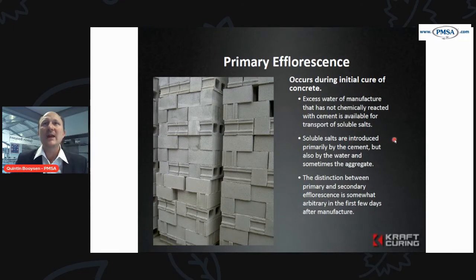The soluble salts are introduced primarily by the cement, but also can be introduced by the water and sometimes by the aggregate. So sometimes you have these salts coming off your aggregates or your water. That's why it's good to have potable water that's drinkable, and aggregates that preferably have been washed in clean water.